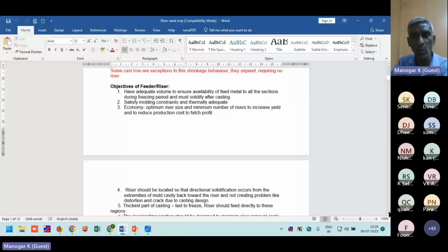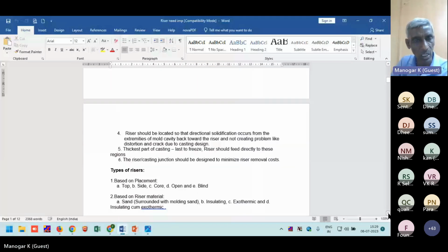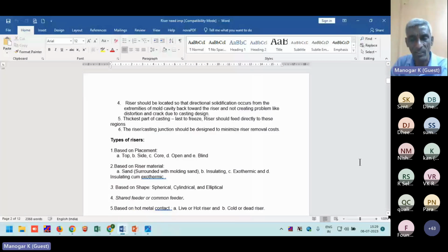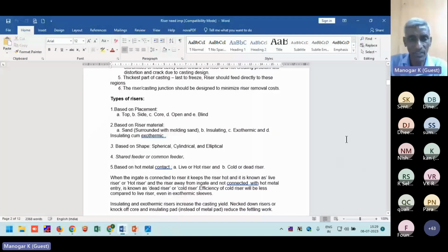Risers should have adequate volume to ensure availability of feed metal to all the sections, satisfy molding constraints and thermal adequacy, and economy of the casting, that will have a higher yield. And it should promote directional solidification. The riser casting junction should be designed to minimize the riser removal cost. Type of riser based on the placement: it is top, side, or core riser, open and blind riser. Based on riser material: sand, insulating or exothermic. And based on the shape: spherical, cylinder or elliptical. And there are shared risers, that is a common riser for 2 junction sections or 2 castings.